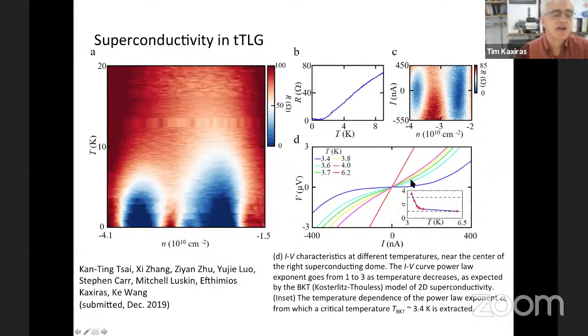Here's the picture experimentally that shows the superconductivity, the voltage versus current picture. The VI curve shows a flat region. And interestingly enough, the critical temperature for superconductivity here is 3.4 degrees Kelvin. This is about a factor of 3 or 4 larger than the bilayer system. So this is very promising that the superconductivity is at significantly higher temperature. Therefore, the correlations are more interesting, stronger, and more promising for actual applications.